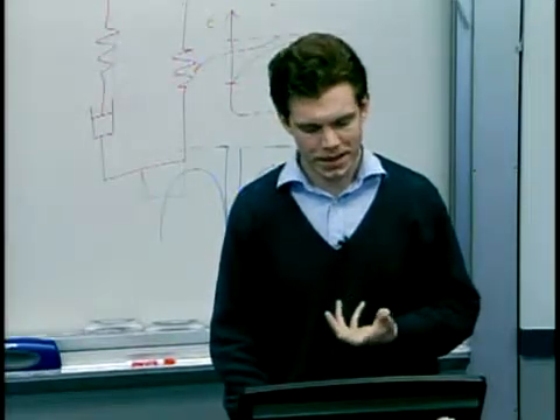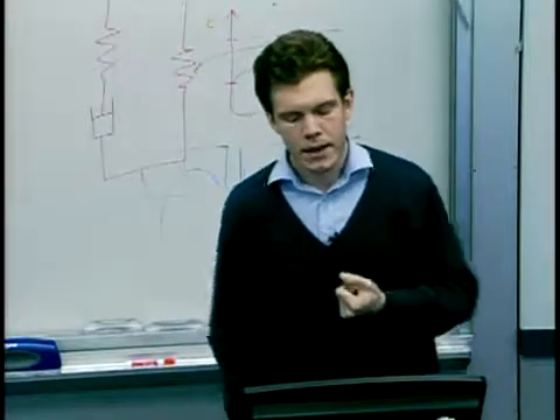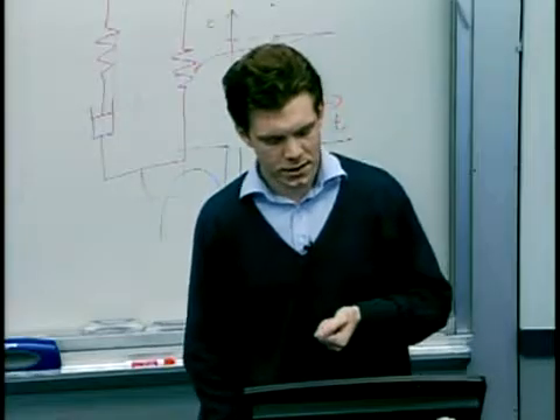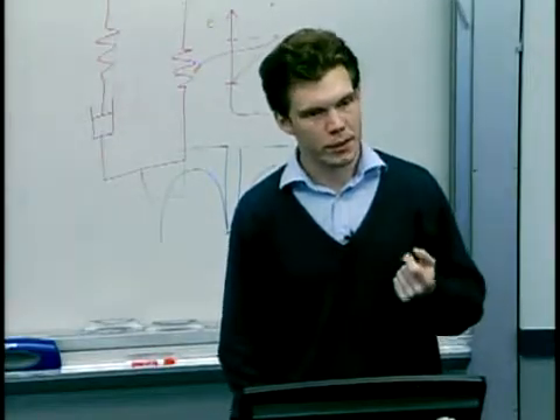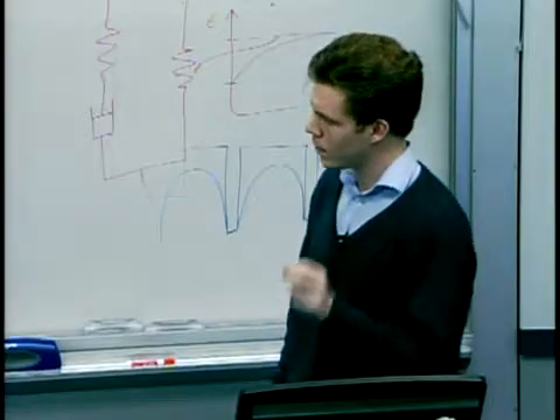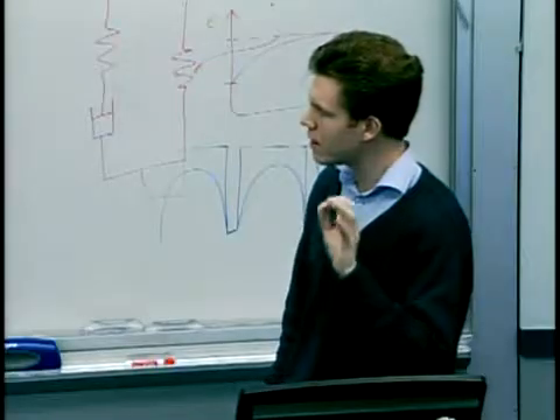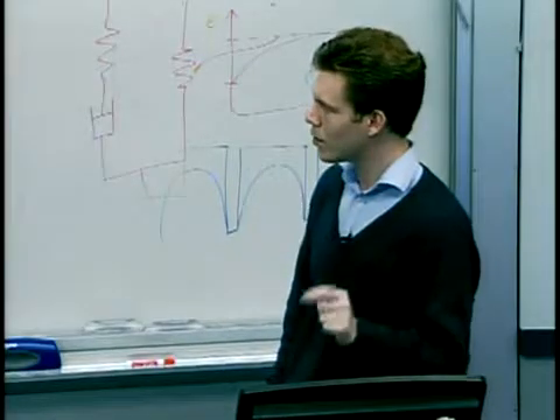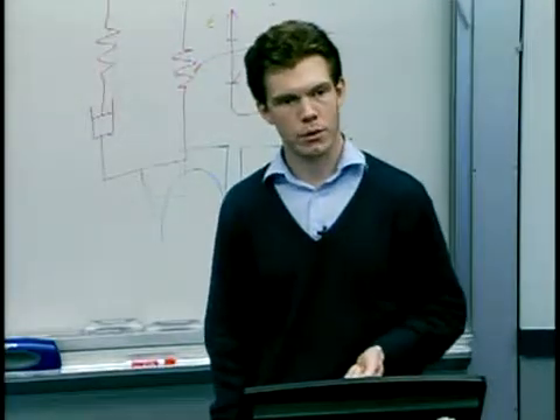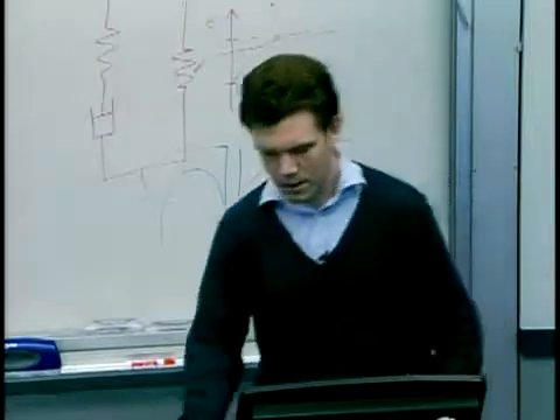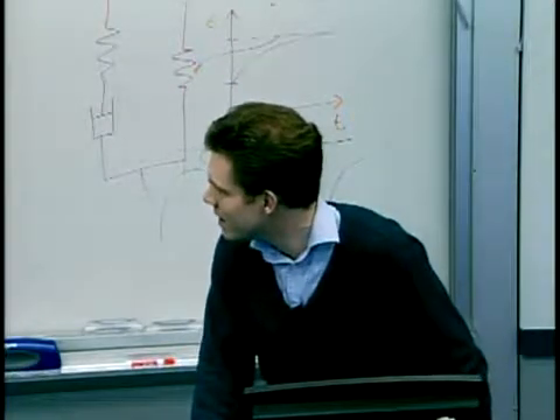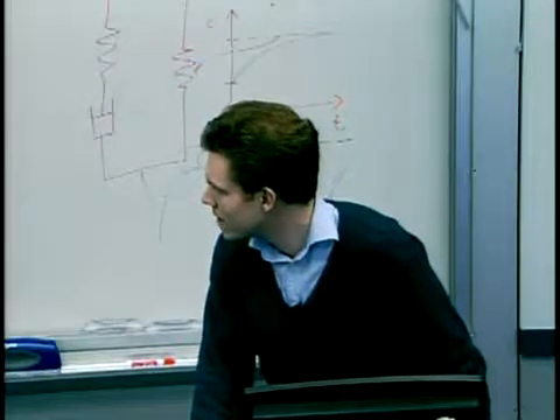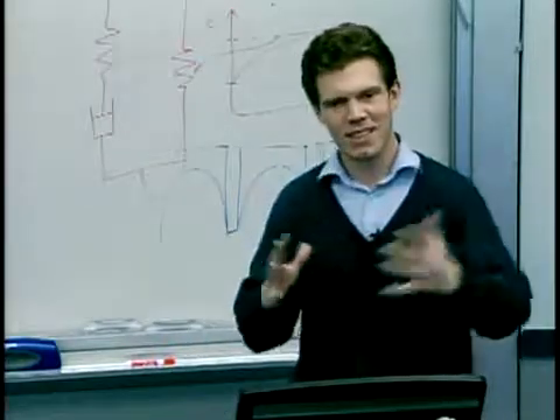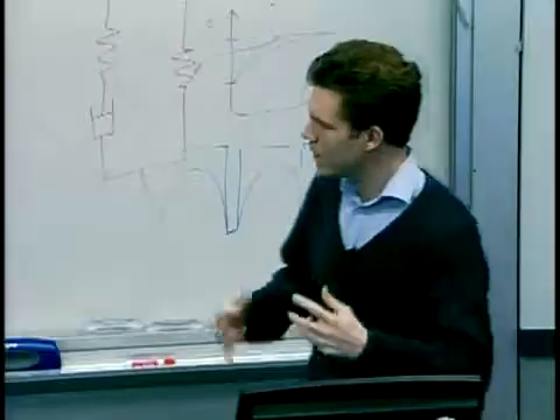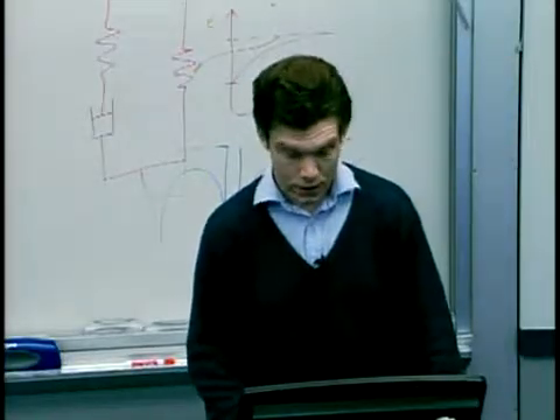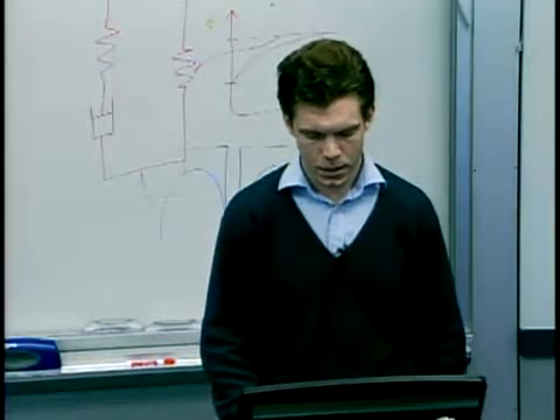olefin polymer called Topas. And this is a material that softens around 85 degrees C. And so we did a 2 to the 4 minus 1 fractional factorial where the four parameters were embossing temperature, peak embossing force, hold time, and the time over which the load was ramped up to its peak. And the astute among you will notice that these variables are not going to be independent, because the average load over the loading time will contribute to the hold time. So it's a rough and ready set of experiments, but nevertheless gives you some idea of what we might do.